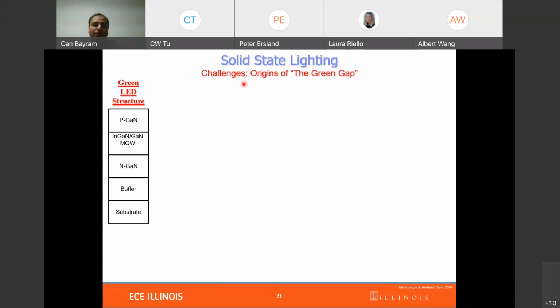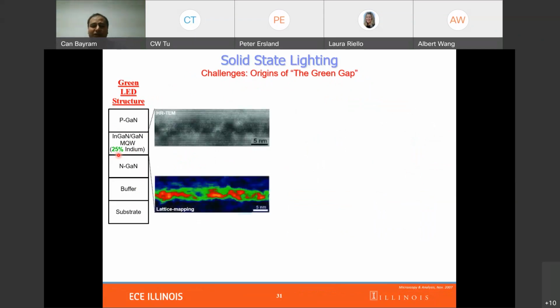Now, let's look at the origin of the green gap. So again, an LED is basically a PIN structure where the active layer is a multi-quantum well. So what I'm going to show here is basically if you have a green LED, you typically have 25% indium. And here are some results of high resolution TEM of these LEDs, where you can see the indium is scattered around.